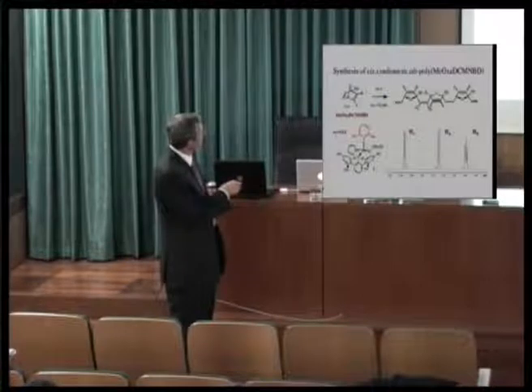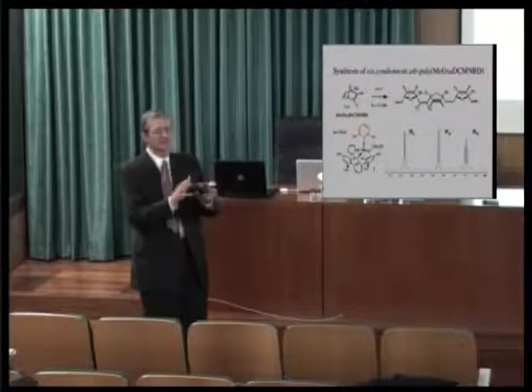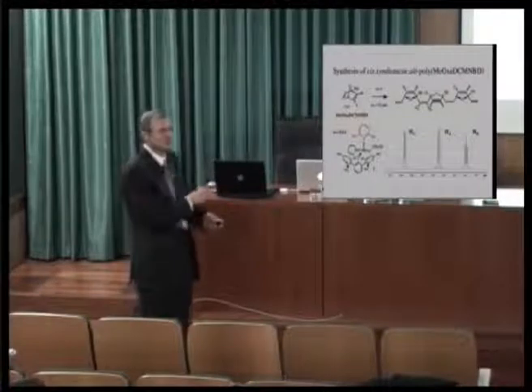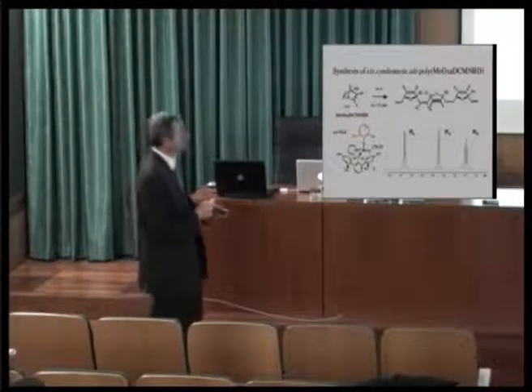These are the three signals for these three protons, two olefinic ones and one up here, as shown here. Not for the adamantylamido, but for the dimethylphenylamido. Everything's very, very sensitive to which amido group you choose and what the groups are on the ligands and what the pyrrolide is and what the metal is and so on. So it's monomer dependent, not surprising. Chemistry is that way.